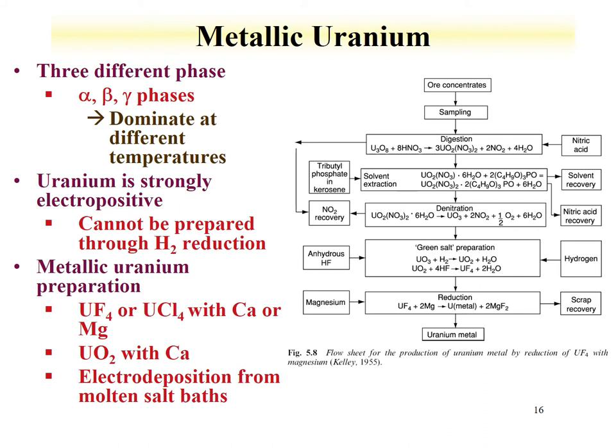As we already discussed, if I want to make uranium dioxide, I can take higher oxides, treat them with hydrogen under heated conditions and make UO2, so that's uranium-4, but the hydrogen will not drive uranium down to the metal. So that means to prepare uranium metal, I have to use a different route. What's done is we make fluorides of uranium. We take those fluorides and treat them with magnesium metal, so a divalent metal or even a monovalent metal would be sufficient to reduce uranium from the +4 to the metal state.